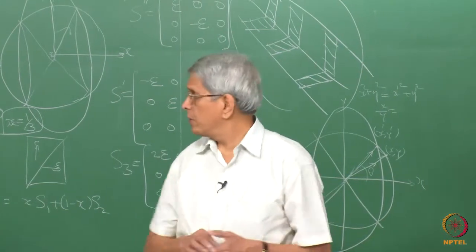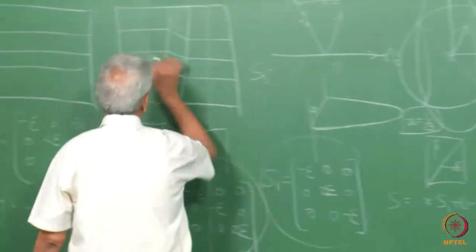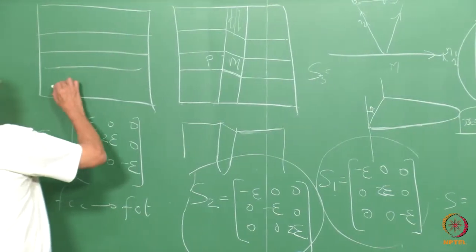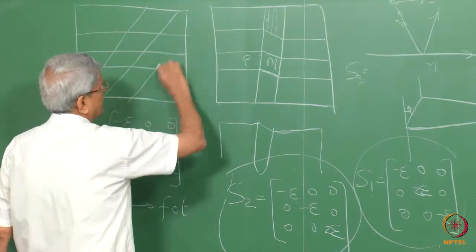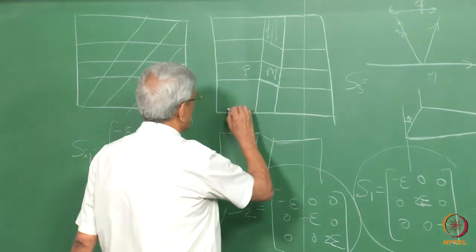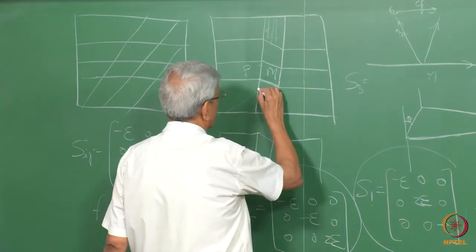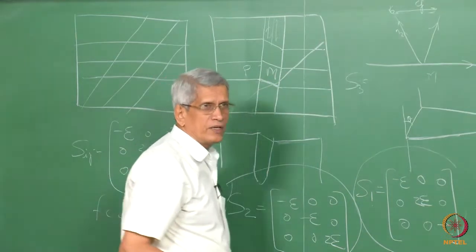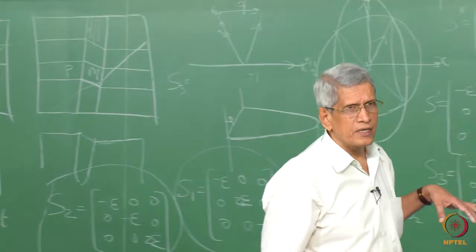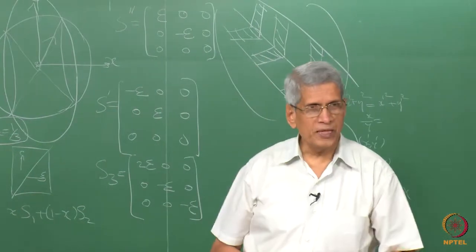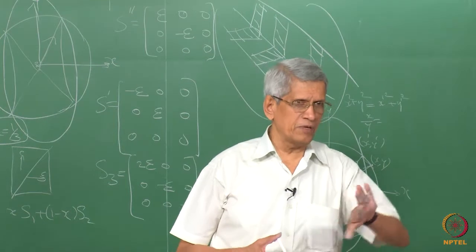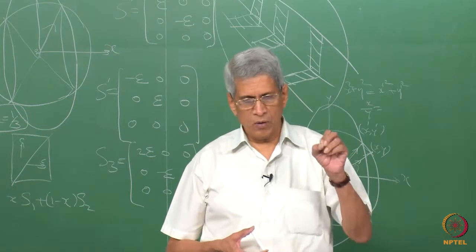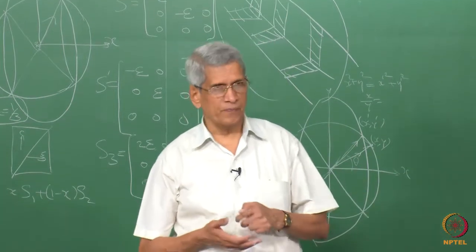How can we find this out? If it is a single crystal, this sort of a transformation takes place. Similar to this, suppose we have drawn another set of lines like this. We assume that line also would have undergone some sort of a transformation. If you know how much is the shift, this is simple geometry, we can find out the macroscopic strain, the angle by which it is tilted. That corresponds to the observable macroscopic strain.